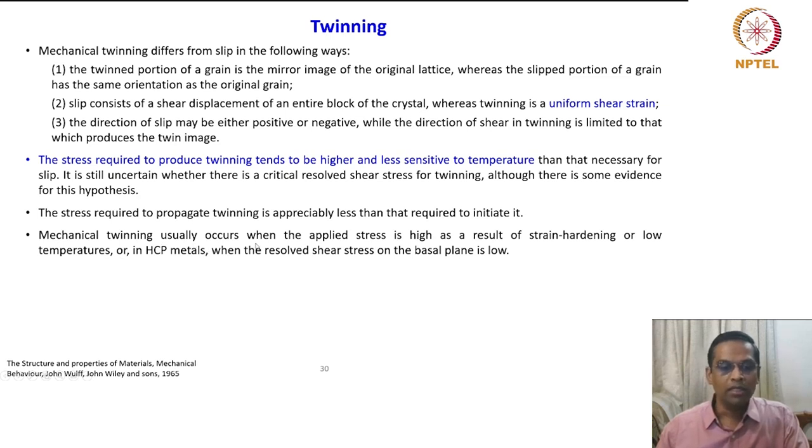Mechanical twinning usually occurs when the applied stress is high as a result of strain hardening or low temperatures, or in HCP metals when the resolved shear stress on the basal plane is low. So this sentence carries a lot of information. What does it convey? Mechanical twinning usually occurs when the applied stress is high as a result of strain hardening or low temperature. That means we looked at the strain hardening ability. When it goes to a very high stage in strain hardening, for example, we looked at the shear stress, shear strain curve for an FCC crystal, where the material experiences the highest stress during stage 3. That kind of situation,